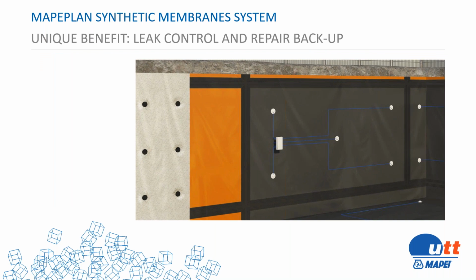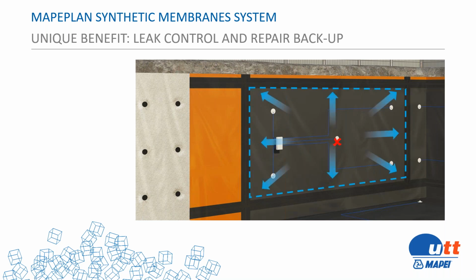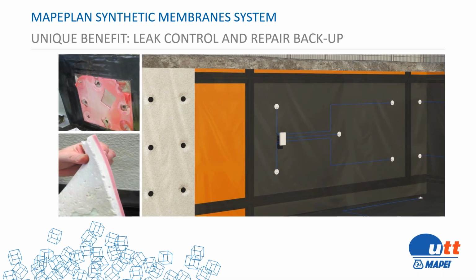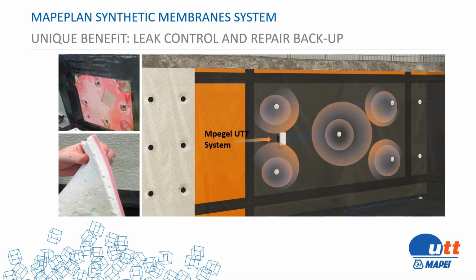As we see now, this compartment has 5 valves. These valves are connected through the blue hose to the junction box. So in case we have any damage, water will start to show from this valve. This is why we call it a testing valve. Very easy: once we start to see water dropping from this blue hose, we connect our injection pump and inject the acrylic gel material through the junction box. In this way, we fill the compartment and repair the leakage from the source. So this valve gives us very good access to the source of the leakage.